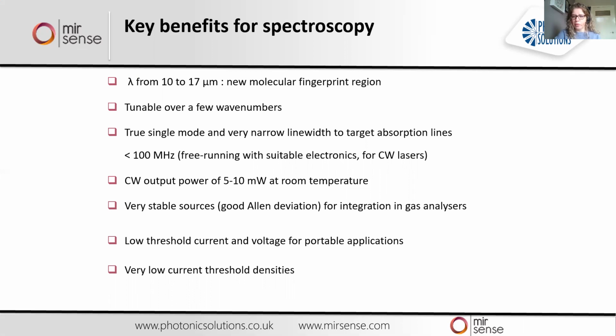The lasers are also tunable over a few wave numbers, which again enables precise targeting of the absorption line of the molecule. As I showed in the previous slide, these lasers have very narrow line width, typically less than 100 megahertz free running. So for spectroscopy, it's extremely important to have narrow line width in order to precisely hit the absorption line of the molecule. The very narrow line width is what drives the very high sensitivity that can be achieved with these QCLs, enabling low part per billion concentration. We've demonstrated in the previous slide that we could measure sub-ppb detection of benzene.